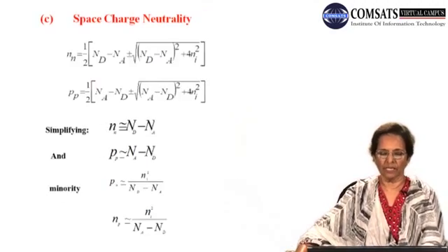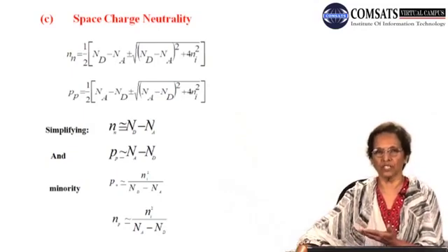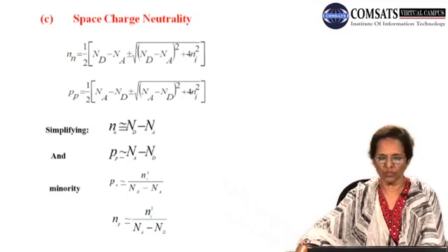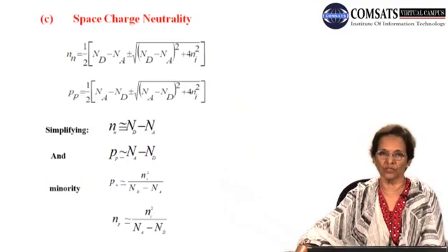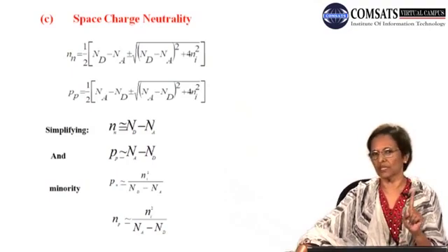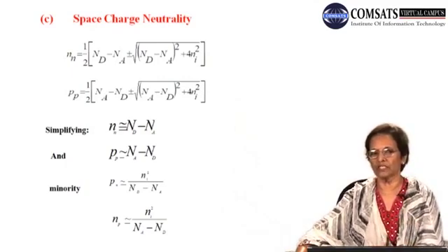Having said that, we can arrive at the following simple relationship by using the expressions of the free charge carrier concentration that we derived using the Fermi-Dirac distribution function. The most important relationship that we would be using in further calculation is that the electron concentration is obtained by the net concentration of donor ions minus the acceptor ions.